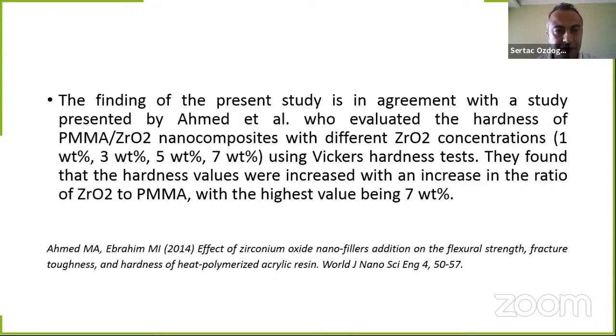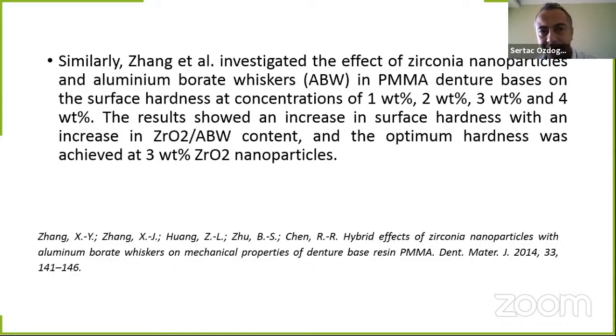7 weight percentage. And similarly, Zhang et al. investigated the zirconium nanoparticles and aluminum borate whiskers in polymethyl methacrylate denture bases at the surface hardness at concentrations 1, 2, 3, 4 weight percentage. The results showed an increase in surface hardness with an increase of zirconium oxide and aluminum borate whiskers content, and the optimum hardness was achieved at 3 weight percentage zirconium oxide nanoparticles.